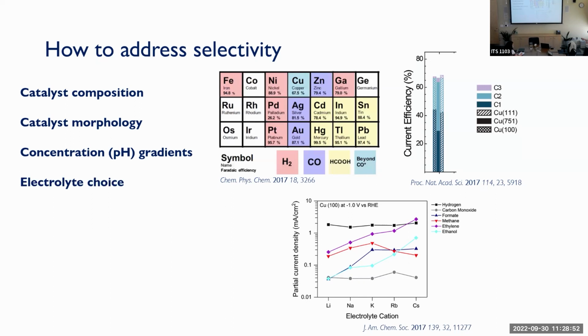Or the electrolyte choice. The electrolyte that you usually use in CO2 reduction is bicarbonate, because you want a buffer when you have CO2. You put it in bicarbonate and you get a buffer, basically. And the pH doesn't change, but you can change the cation of that carbonate buffer that you make. And if you use cesium carbonate, it leads to higher hydrocarbons. And then, of course, the applied potential. I showed you earlier, you have this multi-electron process. The more potential you apply, the more electrons you can get.